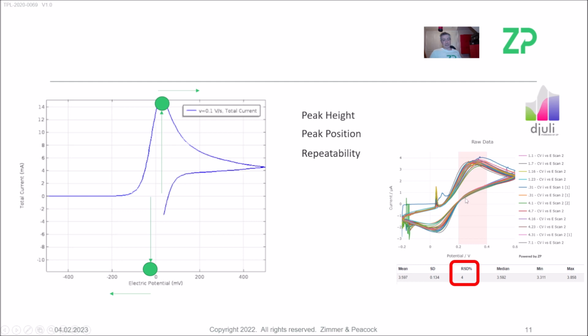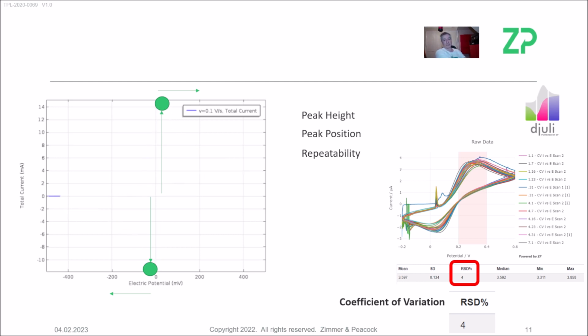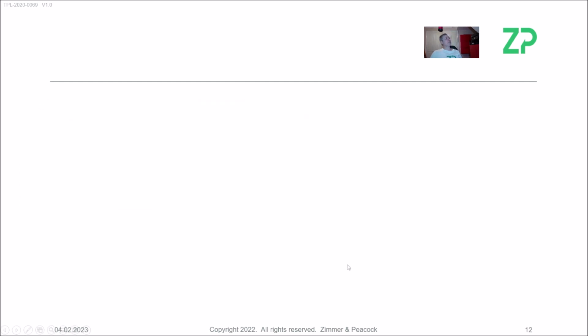get a relative standard deviation here of 4%. So that RSD is just the standard deviation divided by the mean value. You can see it there, 0.134 divided by 3.597. And some people call that the coefficient of variation, so they talk about CV value. Some people talk about relative standard deviation, but we're all talking the same thing. So often with us, if we're screen printing electrodes, then we will get RSDs below 5%, 4% and 3%. These are kind of RSDs that you should be able to get when screen printing.